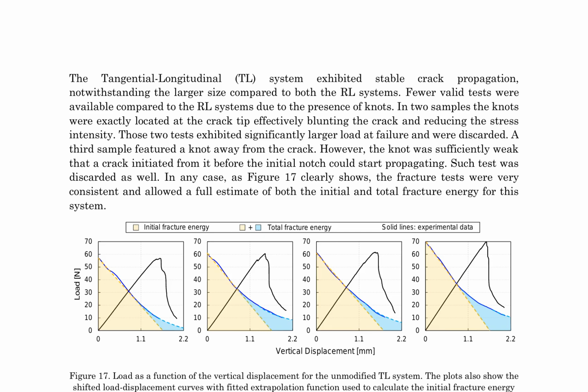A summary of the fracture energies measured for the two unmodified systems is presented in Table 3. The results indicate that both the initial and total fracture energies of the RL system are significantly larger than those of the TL system, consistent with similar tests on spruce wood. The results are extremely consistent, with the maximum coefficient of variation, COV, on the fracture energy being only 10.1%.